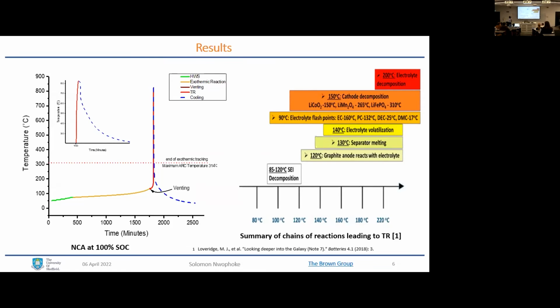So the result, this is a plot of the thermal runaway test on NCA at 100% state of charge. And you see the progression, the trend. The green side shows when the battery was not heating itself. That's the heat-wait-seek period. And then the orange plot shows the region where the battery was heating itself by undergoing decomposition reactions.